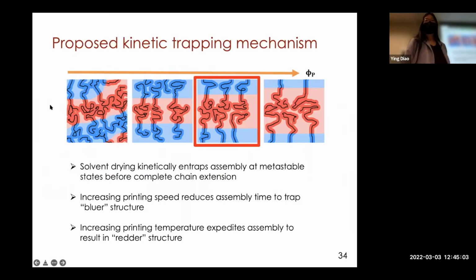Basically, as the polymer assembles, it evolves from blue to red because the spacing is progressively decreasing when we pack the polymers closer and closer. The polymer becomes more rigid. But then if we remove all the solvent before we reach the equilibrium state, we arrest the structure at a bluer metastable state. But then if we heat up the substrate, we push the assembly faster and faster so that we can arrive at a redder state earlier.